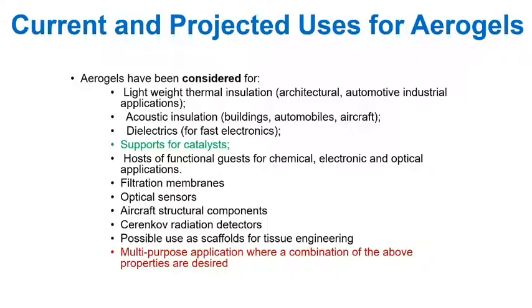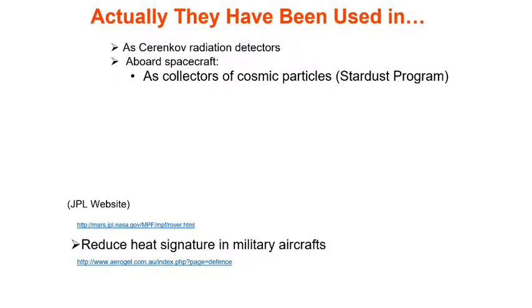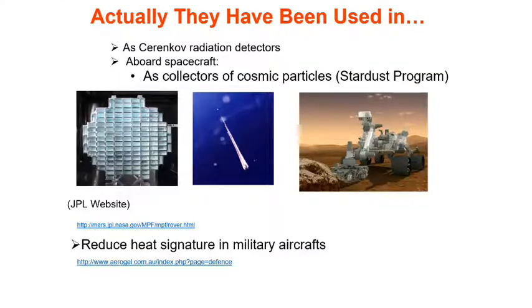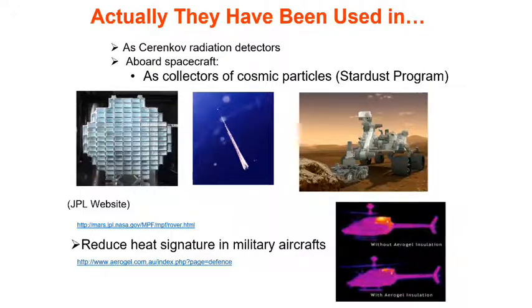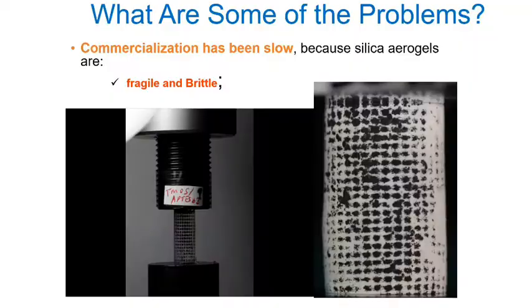Now, one of the most important things is that all these properties can be found within one sample. So you can have all these combinations in just one sample. So they have actually been used, for example, to trap comet dust. NASA used this to trap comet dust. Basically, they made this racket, and when the spacecraft passed through a comet belt, they were able to trap this within the material. Another thing that they have used it for is to reduce the heat signature on an aircraft, especially the special forces helicopter, where they don't want to be detected. They can put a piece of aerogel, and that will basically reduce the heat signature in this case.